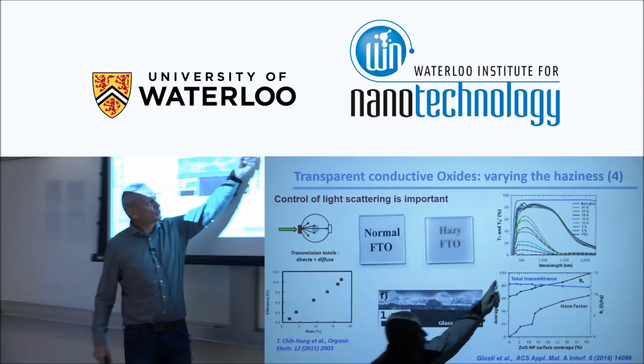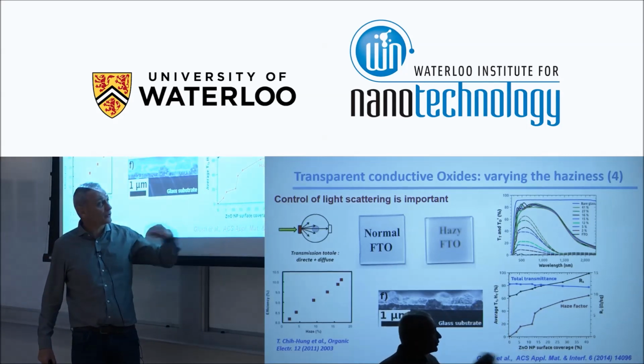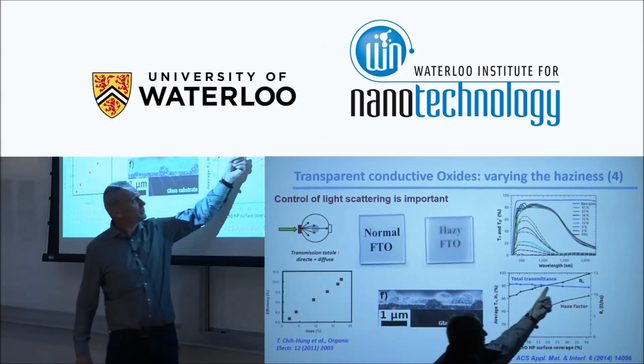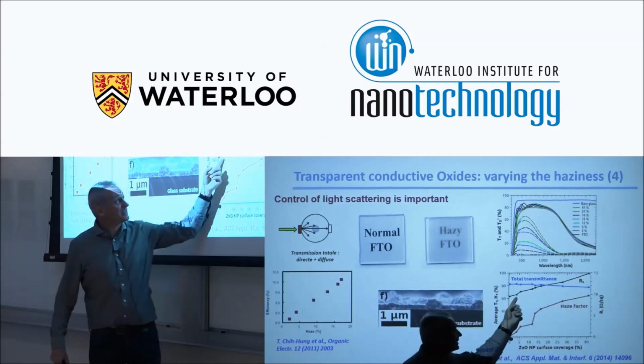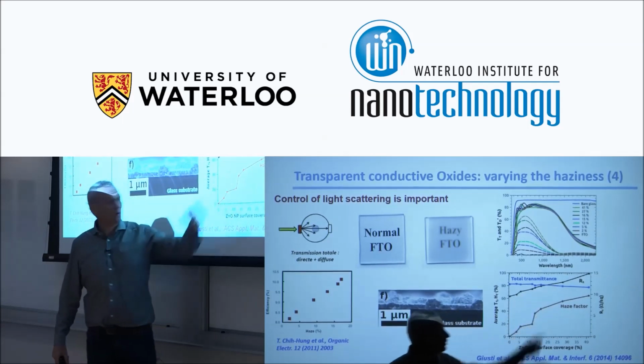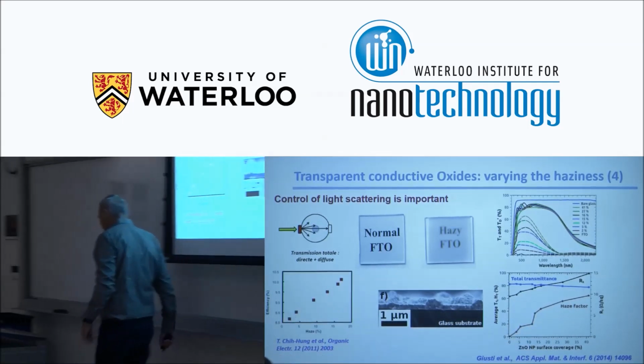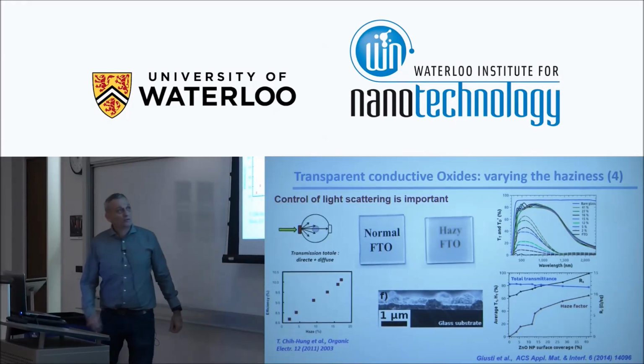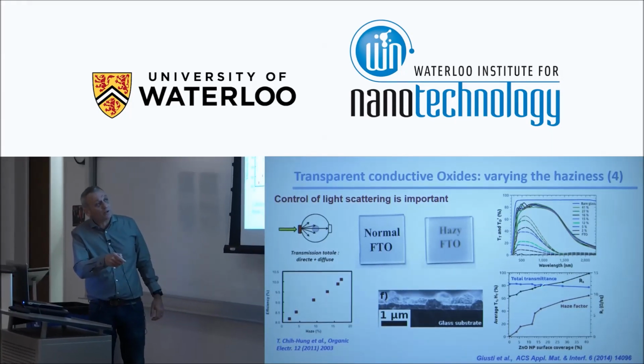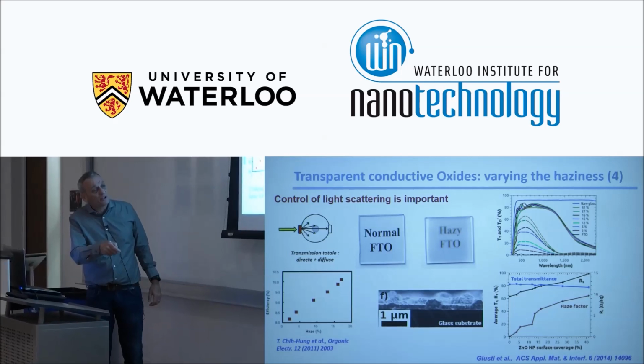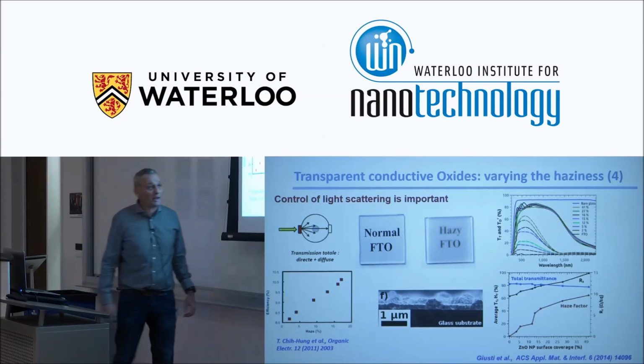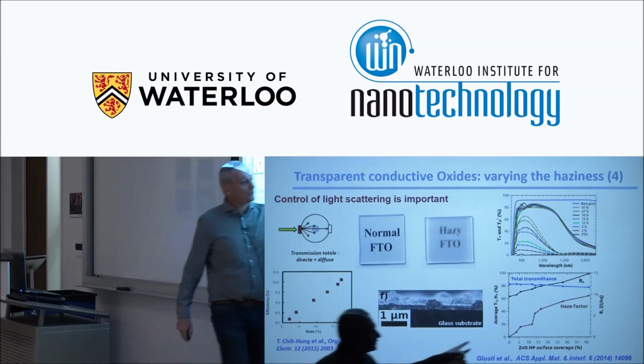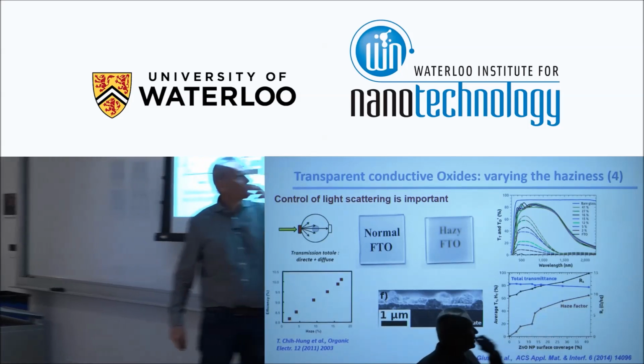This is, for example, the total transmittance versus the zinc oxide nanoparticle surface coverage. Total transmittance is decreasing a bit. Sheet resistance is increasing a bit. And we're able to change quite a lot the haze factor. And with these techniques, okay, we're losing a bit of transparency, we're increasing a bit of sheet resistance, but still in a reasonable range. But we're able to have very large haze factor.